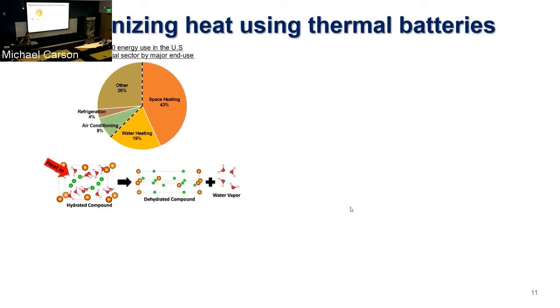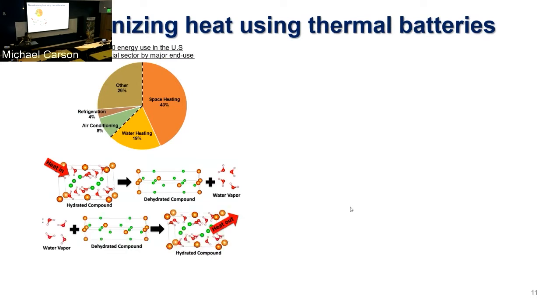So the way we do that is we use these reversible thermochemical reactions. So here I'm showing you what would be like the charging step for your battery. So you have a hydrated salt, which once you drive heat through it, it goes through an endothermic reaction where the salt dehydrates. You get the dehydrated salt and you're left with water vapor. We can then run the reverse reaction, which is you introduce water vapor to the dehydrated salt, which will combine. That reaction is exothermic, and then that heat will be released. So we're looking at storing energy as heat by running these reversible solid gas chemical reactions.